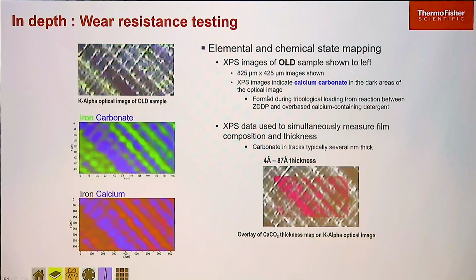so about 9 nanometers in the thickest areas on the surface here. And James mentioned earlier about angle-resolved XPS, which is one way that you can do this when you've got slightly more complex systems. But when you've just got a very simple A on B, overlayer on substrate, two-component system, you don't have to do the tilting experiment. As long as you can see the signal from the substrate, you can directly calculate the thickness of the overlayer, which is really quite useful.